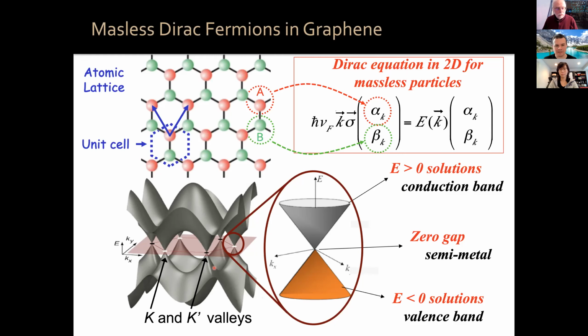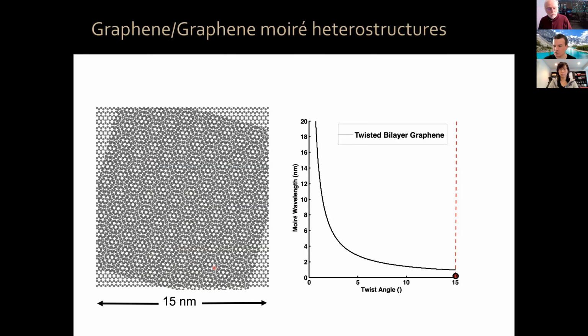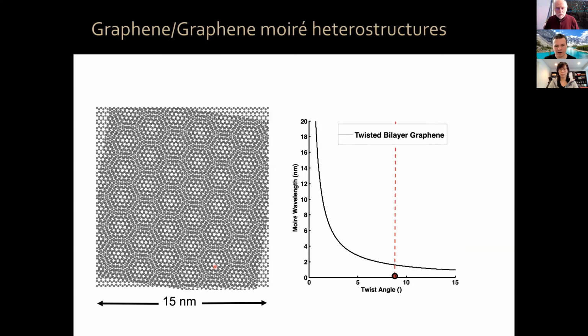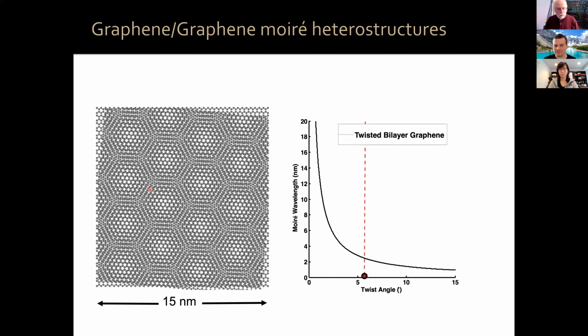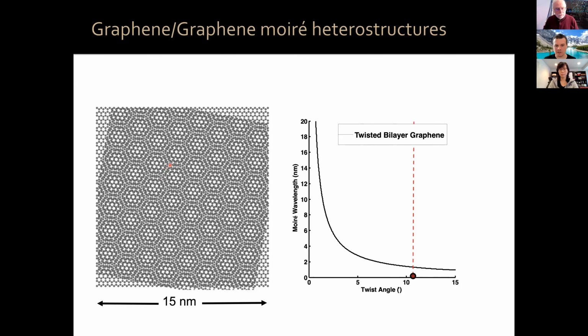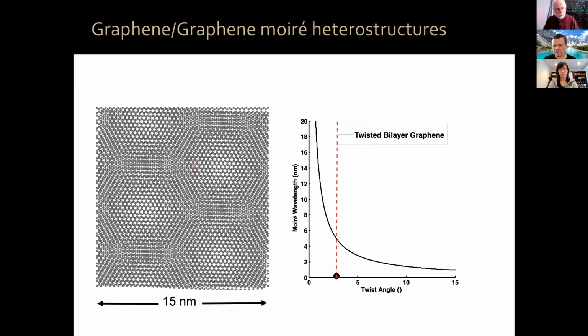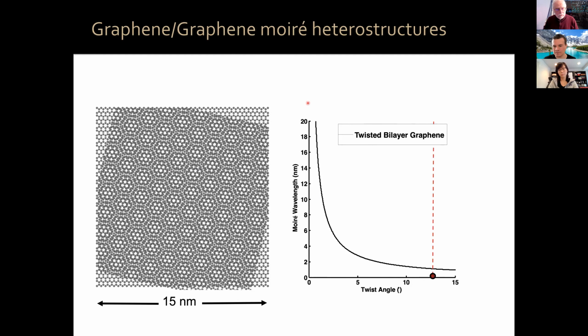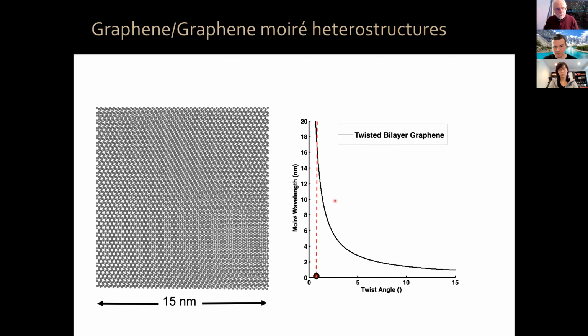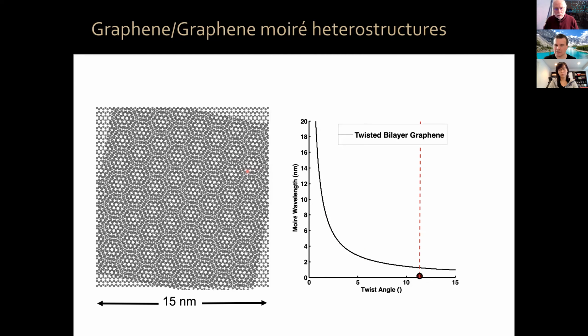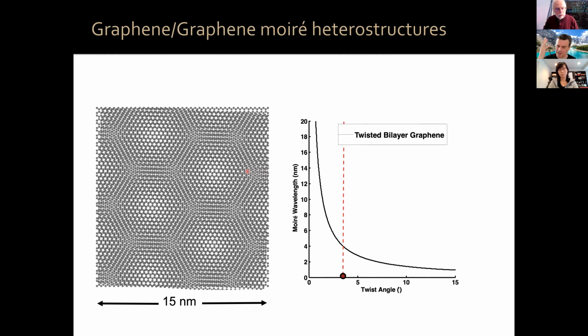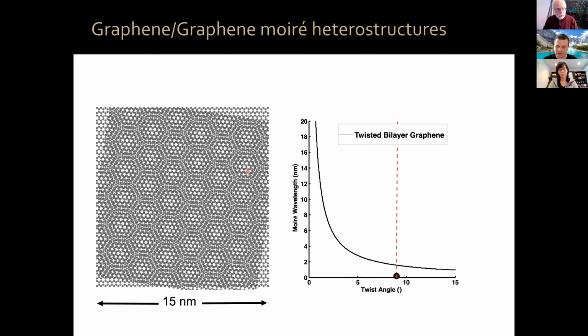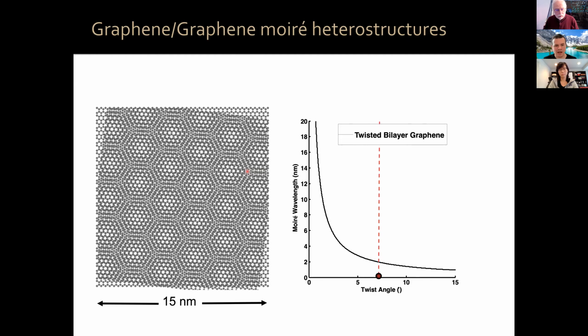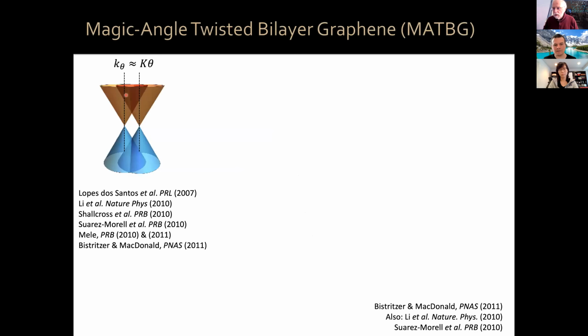Now, what happens if you put graphene on top of graphene and you twist the lattice? Okay, a Moiré pattern forms where the Moiré wavelength, the distance between the soccer balls that you see here in the animation, is roughly proportional to 1 over the twist angle. Okay, now this is what happens in real space. Let's think about what happens in momentum space, and in particular, what happens with the electronic structure with those Dirac cones. Now, I'm showing here the Dirac cone from one layer of graphene and the Dirac cone from another layer of graphene.